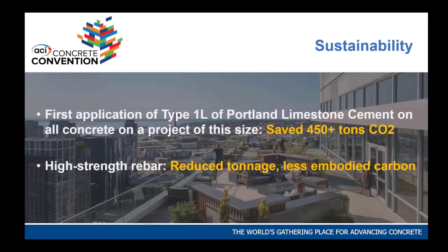The carbon was interesting because by just using Type 1L cement, we were able to reduce about 10%. We did the math on it, about 450 tons of CO2 reduced right off the bat. And then being efficient and putting in transfer beams and all that stuff. People don't realize that a lot of the carbon reduction is the big question, and I always ask myself, you see all these highways and bridges, but you can easily reduce carbon by making your design a bit more efficient, by at least 10%. You always can make your design a bit more efficient.